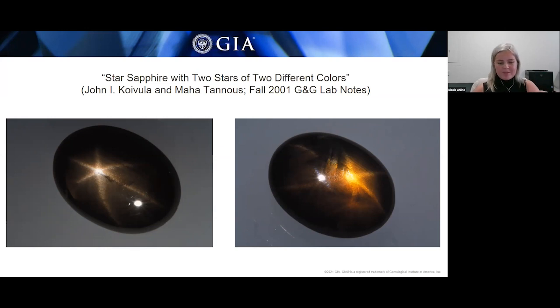So this star sapphire had two distinct 6-ray stars at opposite ends of the same side of the cabochon, and they both have very distinct colors. Seen on the left, one side had a silver color fading into a little bit of brown, while on the other end, on the right side, the stone had a strong golden 6-ray star. The body color of the stone, as well as the depth of the star, were the two factors responsible for this asterism that you're seeing.